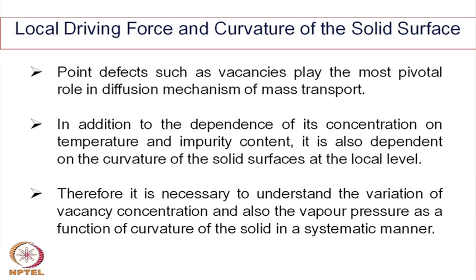Defects are certainly created by increasing the temperature. That is one way of introducing defects. In addition, we have also seen in earlier lectures that by adding impurities of different valency, one can also create vacancies, because of the charge neutrality requirement. So, these are the two known parameters by which one can generate vacancies.